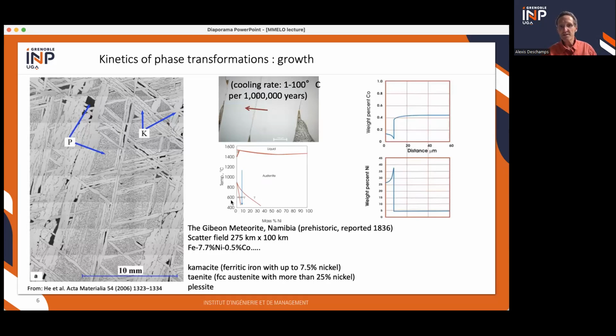And of course, then you have a difference of nickel composition between ferrite and austenite. Of course, it's not called ferrite and austenite in this field, but it's basically the same. And actually, if you take this meteorite and you make a composition gradient profile, you can see that you have large composition gradients in each phase, which means that despite this extremely slow cooling rate, you're still quite far from equilibrium. You don't have flat composition profiles. So it's difficult to get to equilibrium, and then the kinetics is important to understand and characterize.